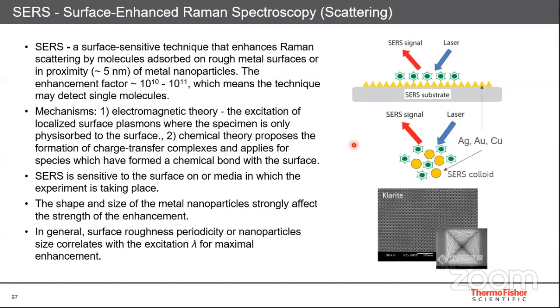So what typically happens is that when the molecule is put with these colloids, silver, gold, or copper colloids, it interacts with them. When the laser light falls upon it, it gives you that surface enhanced Raman signal, and you can see very strong signals of the molecule in the Raman spectroscopy. You just have to use these colloids. The shape and size of these metal nanoparticles affects the strength of the enhancement. How much it will be enhanced depends on what kind of nanoparticles you're using, and in general the surface roughness or the nanoparticle size correlates with the excitation for the maximum enhancement. So you have to see which one gives you the best results.